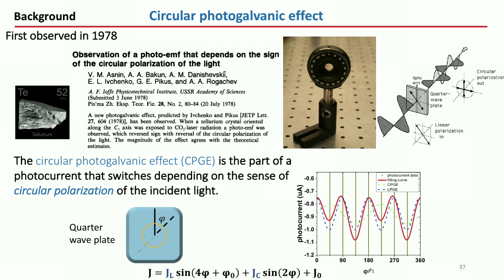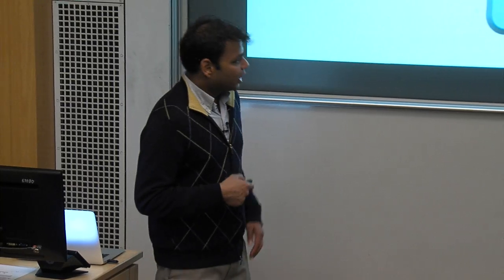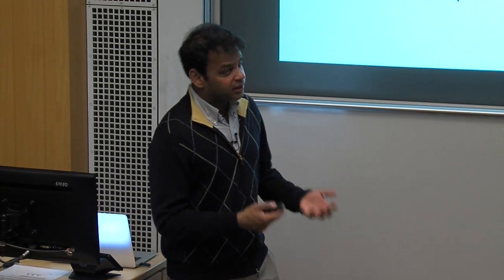And if left and right circularly polarized light produces different photocurrents, that means you have this effect. Otherwise, there's no reason to have different photocurrents for left and right circularly polarized light. Most materials, that's why this phenomenon is relatively rare, will produce the same amount of photocurrent for left and right circularly polarized light. So this basically means you have to break certain symmetries.